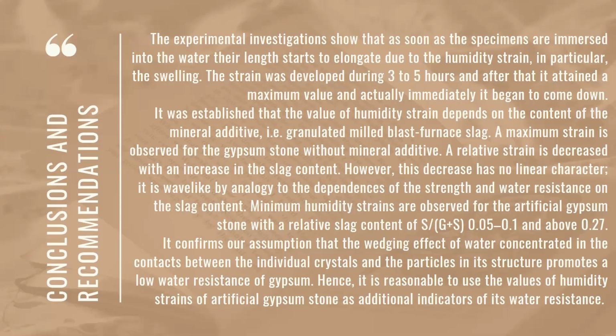It was established that the value of humidity strain depends on the content of the mineral additive, granulated milled blast furnace slag. A maximum strain is observed for the gypsum stone without mineral additive. A relative strain decreases with the increase in the slag content. However, this decrease has no linear character. It is wave-like, by analogy to the dependencies of the strength and water resistance on the slag content.